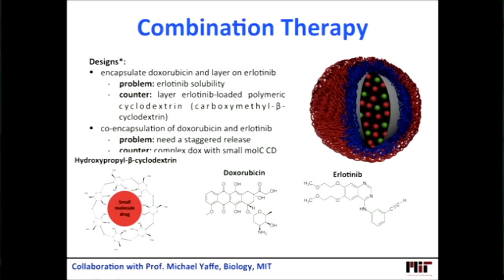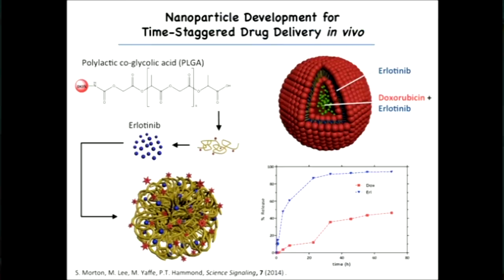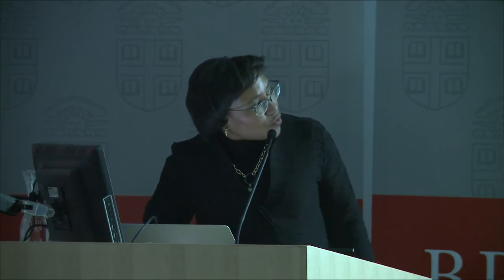And here what we did was do a combination therapy in which we release, in this case, erlotinib drug from the outer layers of our vesicle and release doxorubicin from the inside. And we found that we could actually replicate something like his in vitro dosing mechanism in which we have most of the erlotinib being released in the first 20 hours, and then we get a bit of a pause in that 20-hour period in the release of the doxorubicin before it really begins to come out over the next 20 to 48-hour period. We found that we could replicate a number of the behaviors that he saw in vitro with our systems by doing these combinations in different ways.